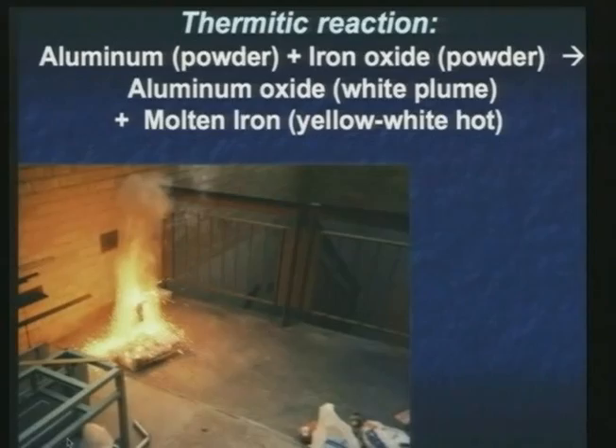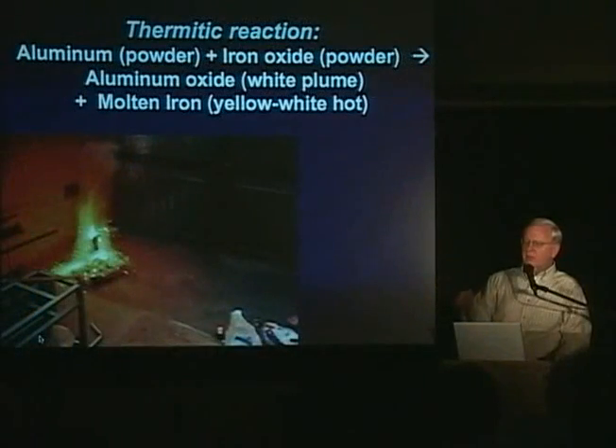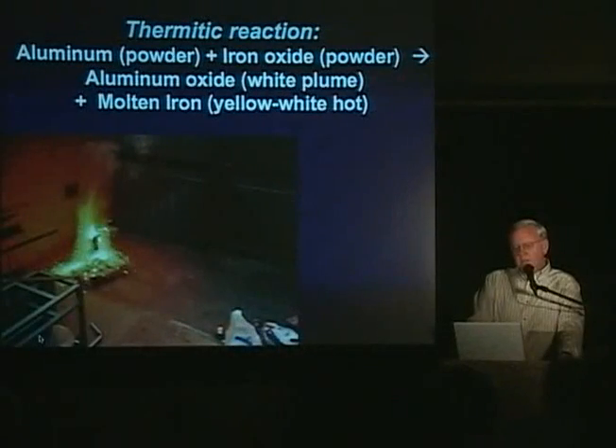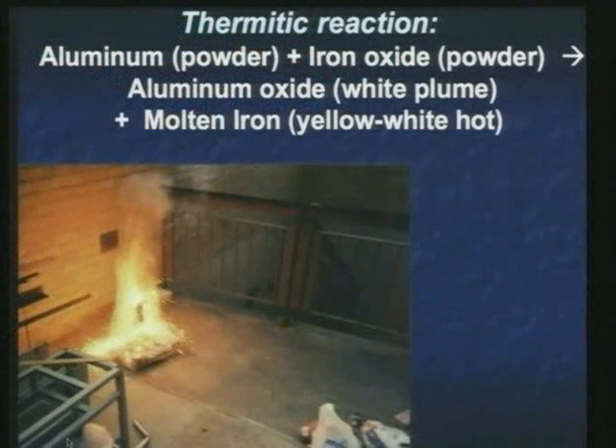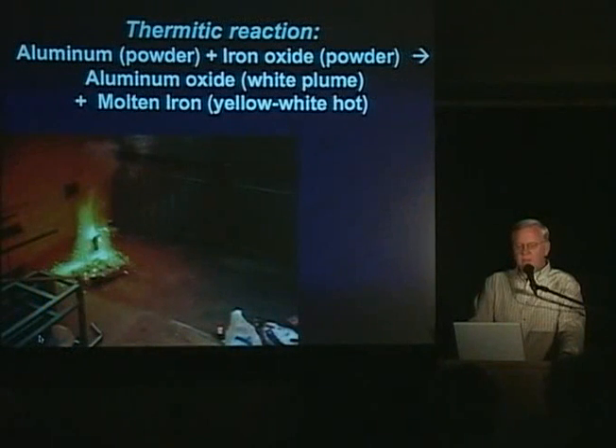You notice you start out with iron oxide, but you end up with iron. What happened? And you start out with aluminum and end up with aluminum oxide. Can you see what's happening? The aluminum grabs the oxygen from the iron oxide, and you get the end products, aluminum oxide, much of which comes off in this plume. It looks like smoke, except it's white. It's quite bright, and it floats away, a fine white plume. And the molten iron then forms, reduced iron.